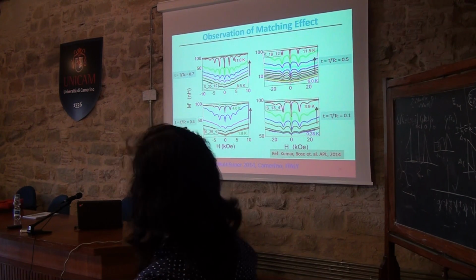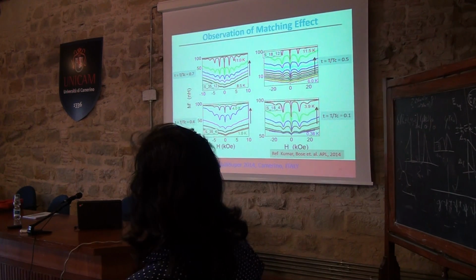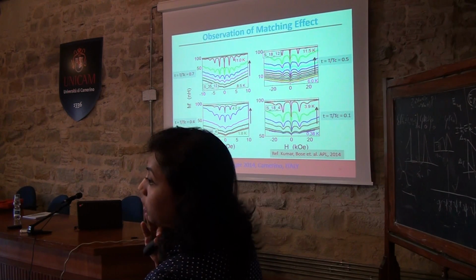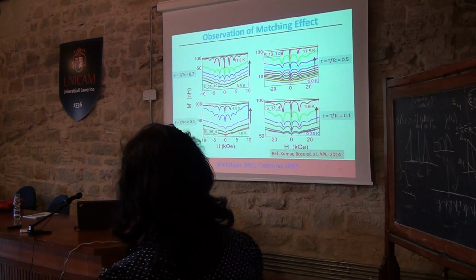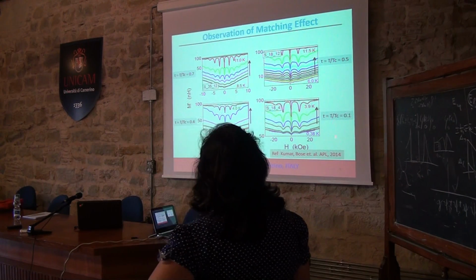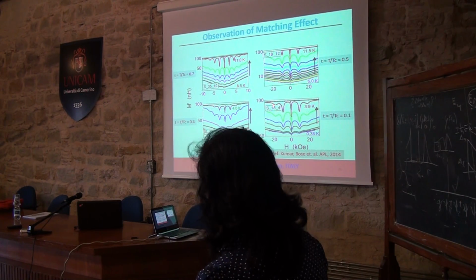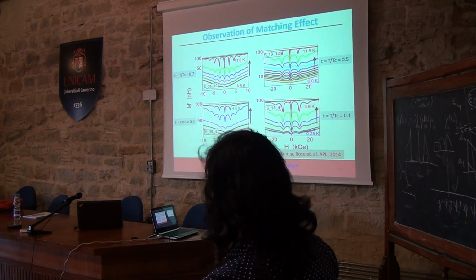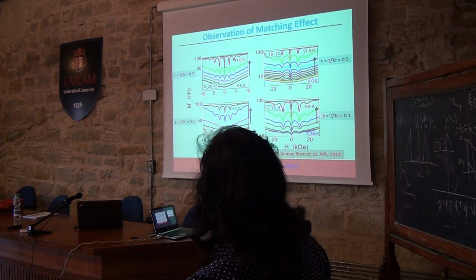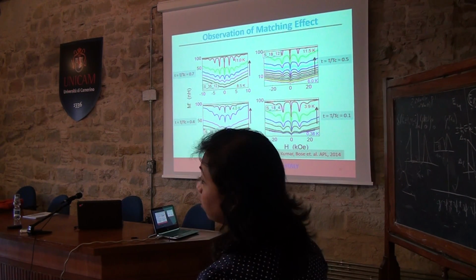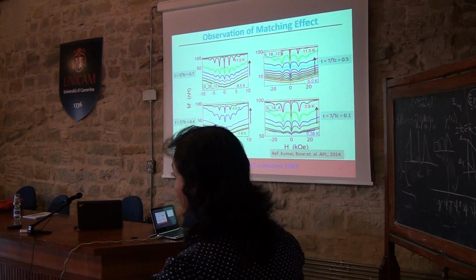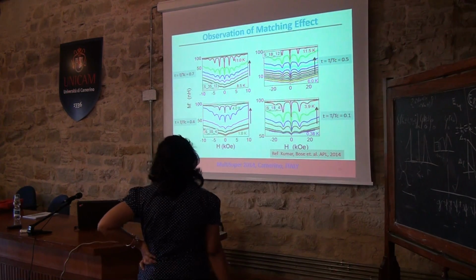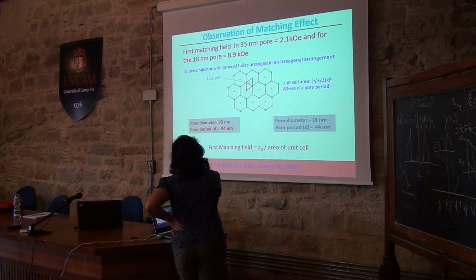All previous measurements, as was done by transport measurements, observed matching effects only to about 90% of TC. When you see that for a sample which has got the lowest pore diameter and the highest disorder, that is the lowest TC, the matching effect is surviving almost to 10% of TC. So it's really surviving deep in the superconducting state.